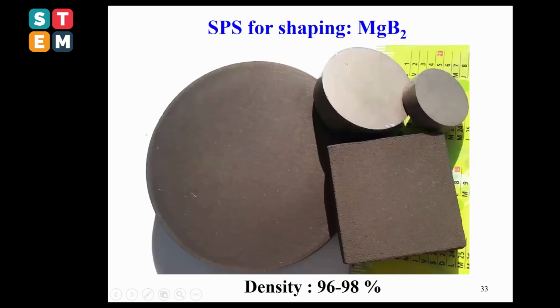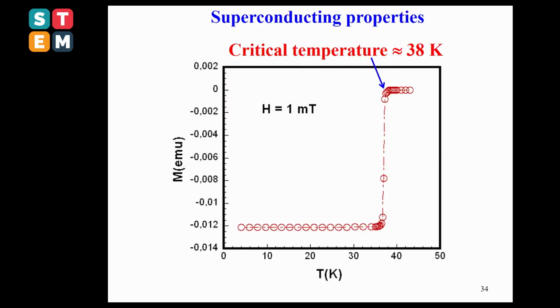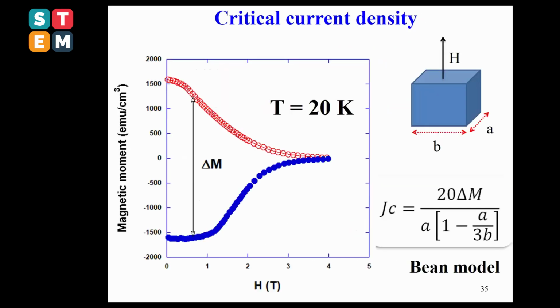Well, these are the various shapes you can produce easily by using SPS. The density can go up to 98%. And regarding the superconducting properties, the TC is around 38K for this material. You have here the temperature dependence of the magnetic moment with the TC.